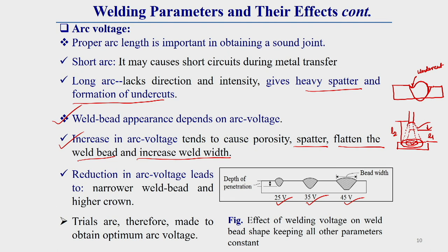Here one thing we have seen is that the change of penetration, that means the depth of penetration, is almost marginal. Do you see this depth of penetration? It's a marginal change. But with an increase of voltage, the bead becomes flatter and its width becomes more and more. That we can observe from here. Why it is so, I have already discussed.